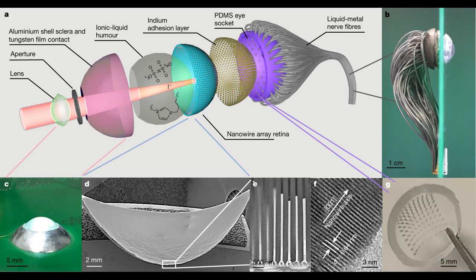The researchers demonstrate an artificial visual system using a spherical biomimetic electrochemical eye with a hemispherical retina made of a high-density perovskite nanowire array grown using a vapor-based approach. An ionic liquid electrolyte was used as a front-side common contact to the nanowires, and liquid metal wires were used as back contacts to the nanowire photosensors, mimicking human nerve fibers behind the retina.